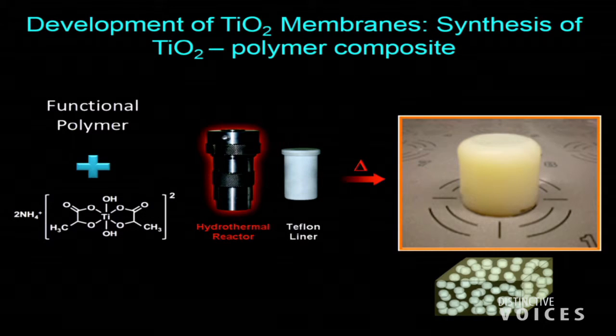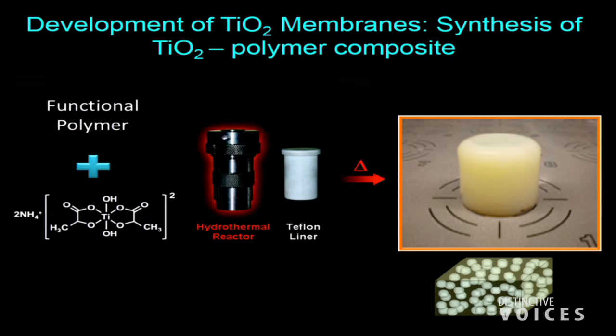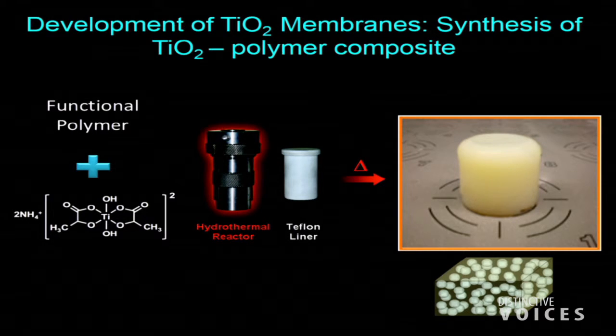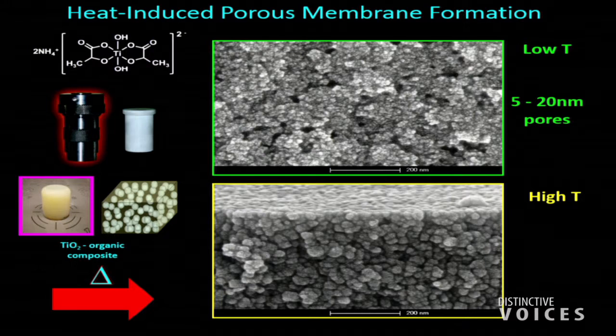We added a polymer to this reagent that I showed that diagram of its chemical structure, put it in these reactors. These reactors are called bombs, by the way, and I never put that in email. I call them autoclaves. Anyway, so we mix these two together and we get tater tots. So these tater tots are polymer, here's a little schematic of it, that is embedded with these little nanoparticles of titanium dioxide. And then we take these tater tots and we can slice them up into little thin discs. So let me count how many are here so I make sure I get them back. Okay, six.